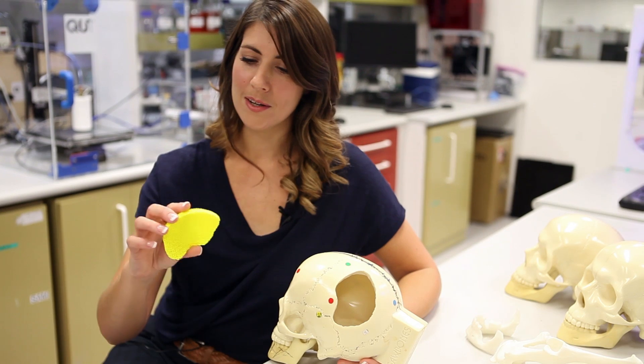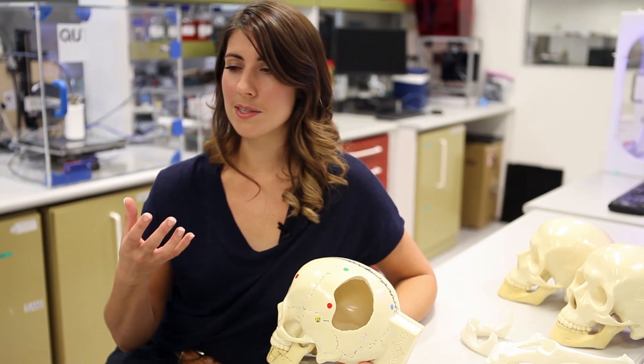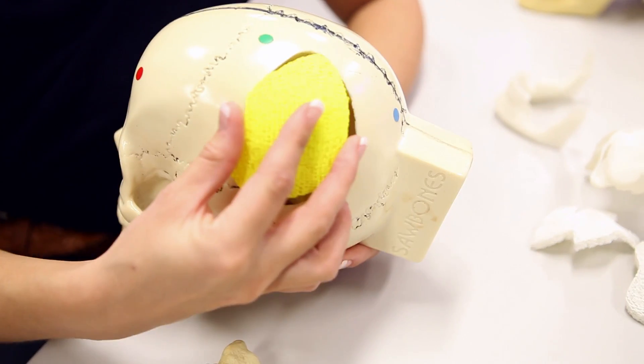Instead of just creating a resorbable plastic implant, we can create this in a 3D printer and at the same time we can add growth factors which stimulate new tissue formation, and we can add stem cells from the same patient that's on the operating theatre. We can put that into the scaffold, printing those at the same time to create a scaffold material that has stem cells and growth factors in there that we can then implant back into the patient.